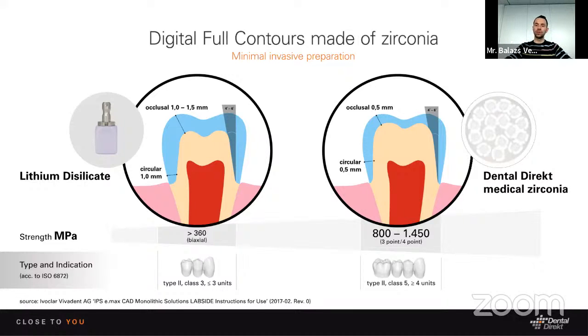And a really important part next to that: when we analyze the flexural strength, with the zirconia material we are still much higher in stability than the E.max material. And if we look at these restorations in the long term, a restoration made from zirconia material will always be much more reliable.